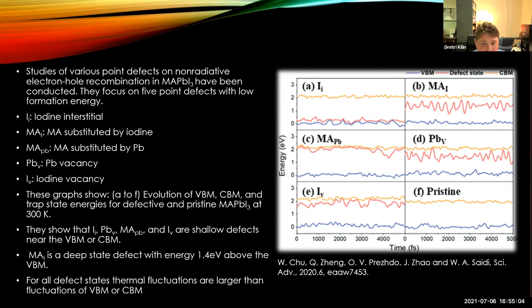Yes, they experience larger amplitude of elongations, the bond distances around the impurity. And the energy is not just thermal quantum. It is potential energy surface as a function of elongations. So all host lattice atoms perform collective motions of smaller amplitude. And if the same amount of thermal energy is communicated to just one or two interatomic bonds, they experience larger amplitude elongation, and they travel much further away from the equilibrium on the potential energy surface. But what I'm saying is not the ultimate truth. The active search for the interpretation of this phenomenon is going on. Okay. Thank you.